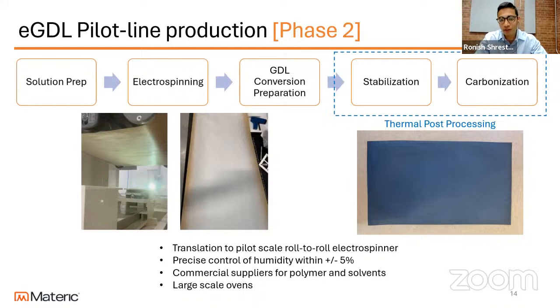The choice of polymer is very important because even if we switch from a lab scale polymer of the same molecular weight to a larger scale polymer of the same molecular weight, there might still be other differences in the polydispersity index. So making this suggestion in the beginning is very important. So we do that. And then also the choice of solvent, similar instructions with the choice of solvent.